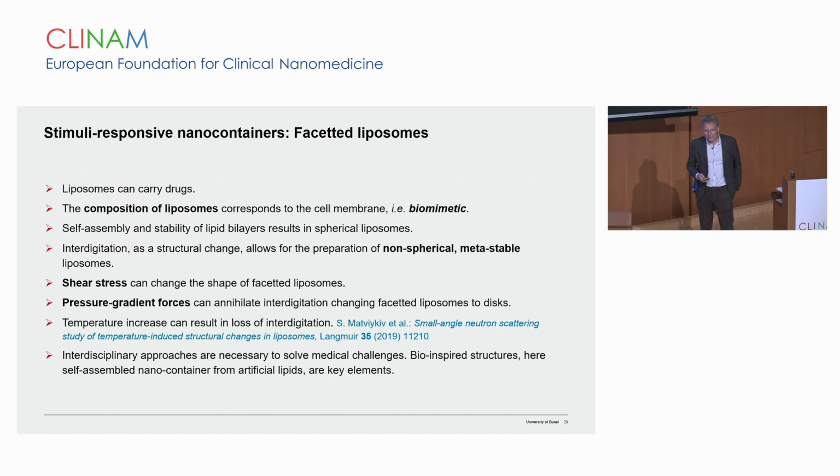But the pressure gradient forces can annihilate interdigitation, changing faceted liposomes to discs that I have not shown, but maybe on the next slide I will show it. And also the temperature increase, so another physical trigger, can result in the loss of interdigitation, as demonstrated by another PhD student of my team, Sofia Matviykiv, and she has shown that very nicely. And thereby you see that interdisciplinary approaches are necessary to solve medical challenges, and bio-inspired structures, here the self-assembled nanocontainers from artificial lipids, are key elements.